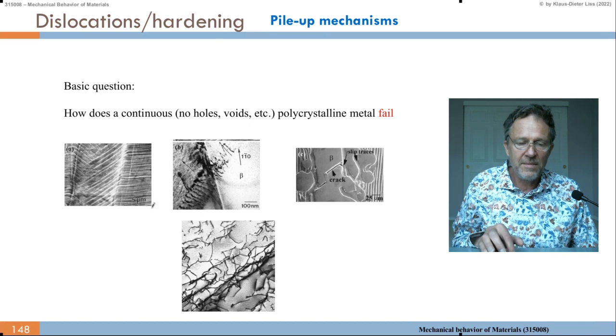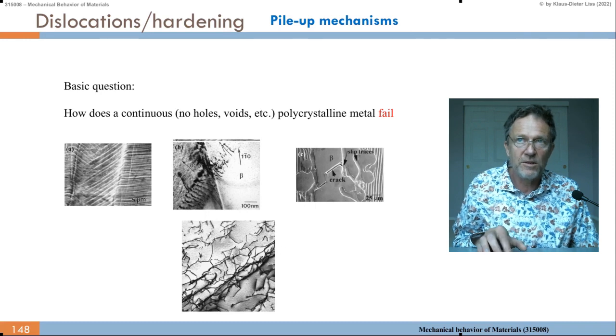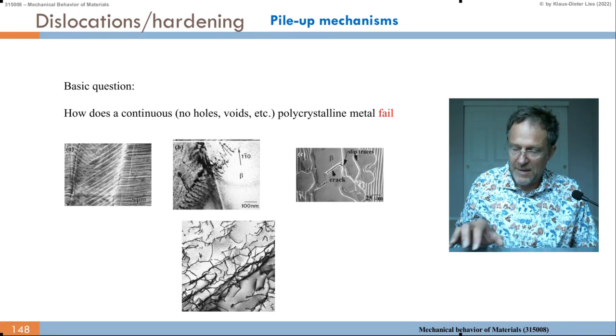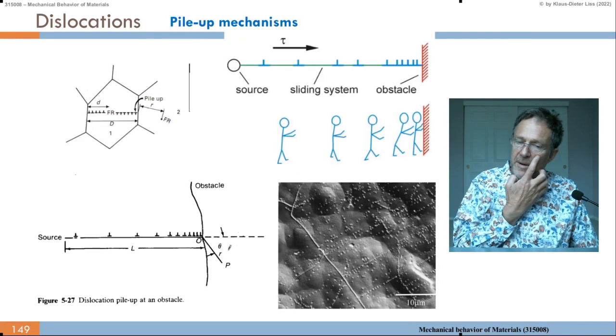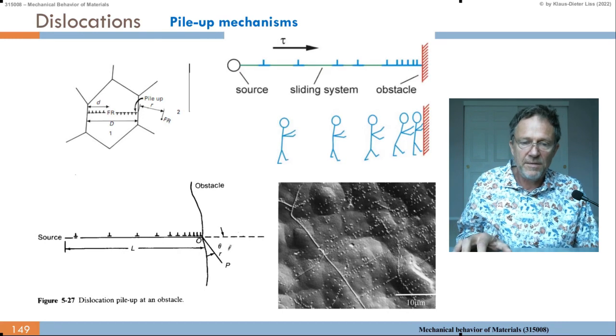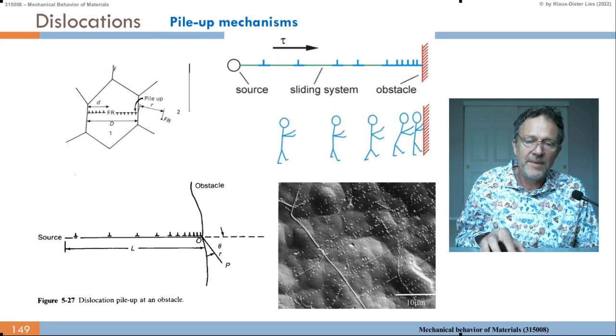We get here the introduction of dislocations, maybe also twin planes, and they accumulate, and eventually you get these micro cracks or nano cracks, where you have accumulation of dislocations. And then these planes or regions of high concentration of dislocations, where it becomes very hard for the dislocation to move. So if you further apply shear stress there, then it may lead to a crack. First a nano crack, and then they can grow to larger macroscopic cracks. So we need to accumulate the dislocations here at the grain boundary.